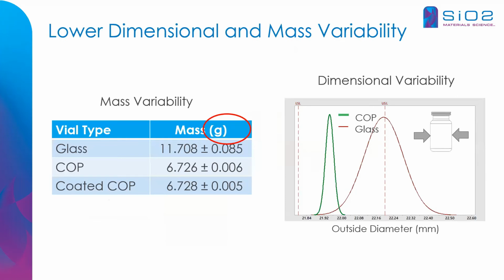And as you see here, here is just another measure of our consistency. On the left, the mass variability, and you can see that we're more than an order of magnitude more consistent, with less mass variability compared to glass. And then also the dimensional variation, where we're measuring the outside diameter. These two combinations make the heat transfer much more consistent with the SiO2 container.